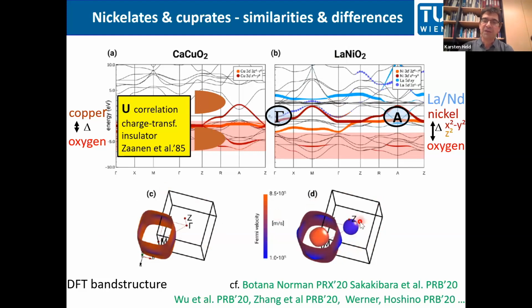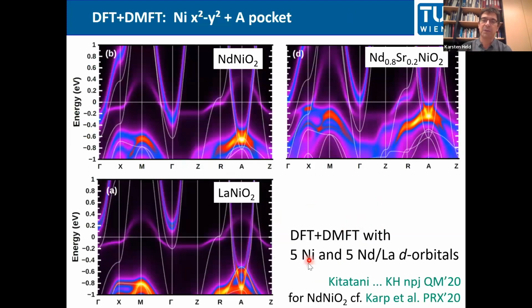Now, again, that is just a DFT picture. We now have to look into what correlations are doing. And to this end, we have done fully fledged DFT plus DMFT calculations with 5 nickel and 5 neodymium d orbitals taken into account. And that is the result here. It's a relatively small window around the Fermi level. In white dots, you see the x squared minus y squared and the other orbitals of the DFT. And the false color is the DMFT spectral function. So you see here the renormalization by about a factor of 5.